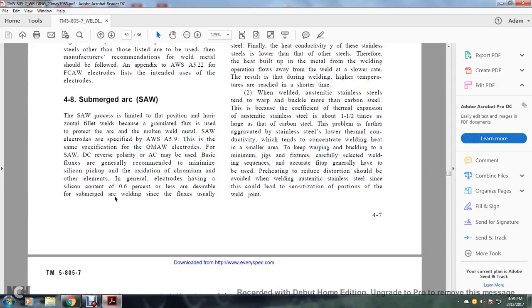Alright, the submerged arc welding process is limited to the flat position and horizontal fillet welds because of the granulated flux used to protect the arc and the molten weld material. Submerged arc welding electrodes are specified by the American Welding Society A5.9, the same specification as gas metal arc welding. For submerged arc welding, DC reverse polarity or AC alternating current may be used, but the AC